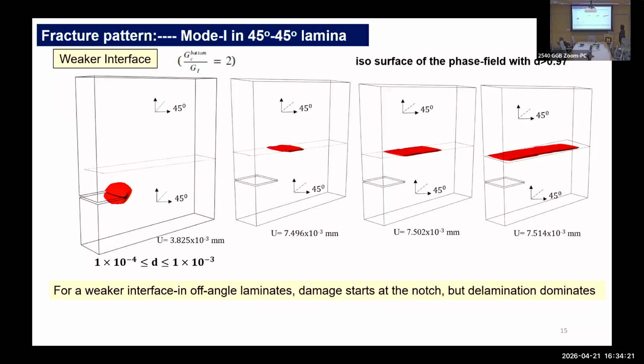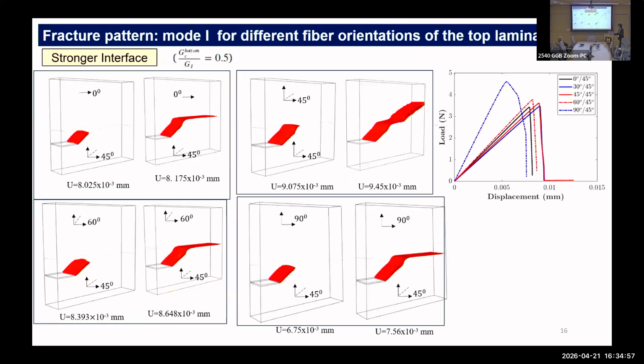So in this particular slide, I'm showing you the case when the interface toughness is weaker than the bottom lamina toughness. And you see what is happening. The crack starts at the notch tip, the damage starts at the notch tip, but it does not propagate. Instead, another crack starts at the interfacial location, and the delamination continues to propagate. So delamination becomes the dominant failure mode. So if the interface toughness is weak, then you will always see delamination, at least under this uniaxial tensile loading condition. This is mode 1 loading, okay?